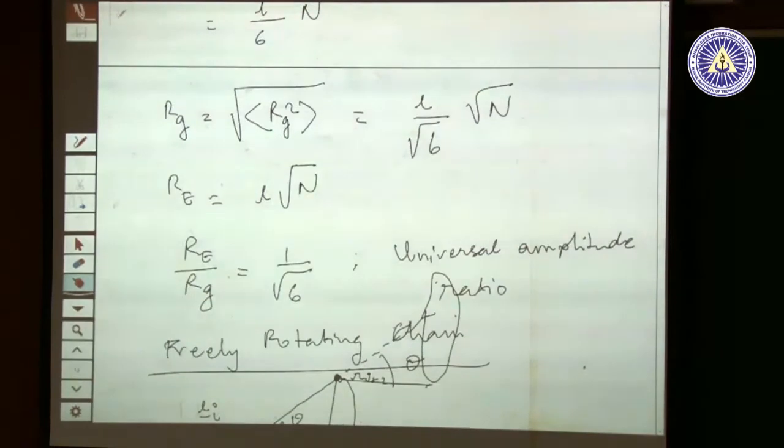So we will see later on, I don't think I will have time, there is something called a Flory-Fox constant that has to do with zero shear rate viscosity divided by the radius of gyration with appropriate units. That's a universal ratio, and polymer solvent systems independent of the chemistry have been measured to have the same value predicted by theory. In fact, if you do not put in all the proper physics on a molecular scale, you will not get the experimentally measured value.